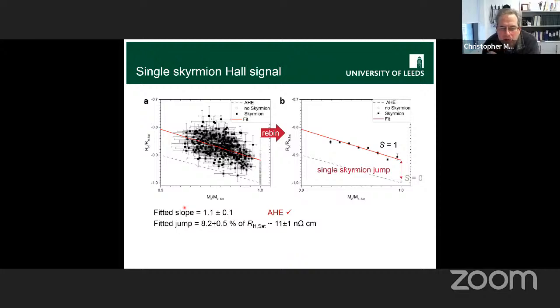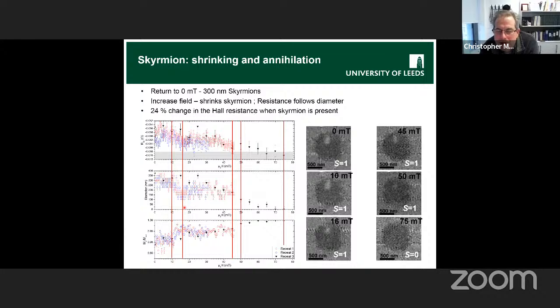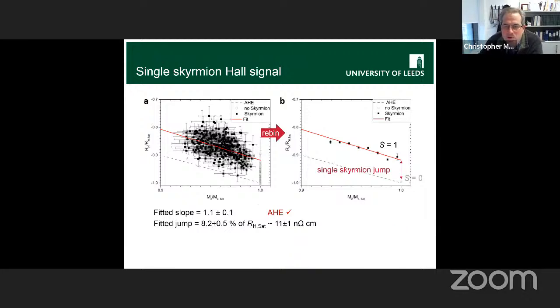Well, maybe this is a good example to go back to. The situation here is we've got a single skyrmion in our disk. As we apply this field, we can squeeze it so it gets smaller, and eventually it disappears. As we measure the Hall signal while that happens, we're squeezing this skyrmion so it's getting smaller and smaller, and the magnetization is growing, approaching saturation, because this little reverse region is getting smaller. So we see this gradual change in the Hall signal, and that's exactly what you would expect from the anomalous Hall effect, because as you squeeze this thing, there's less reverse magnetization.